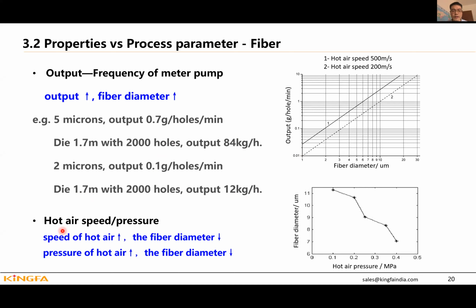And second is the hot air speed and pressure. In this figure, the line 2 hot air speed is 200 meter per second. Line 1 is 500. So from line 2 to line 1, the fiber diameter will decrease. It means the higher the hot air speed, the more the fiber diameter will decrease. Also the pressure: if the hot air pressure increases, the diameter will also decrease.